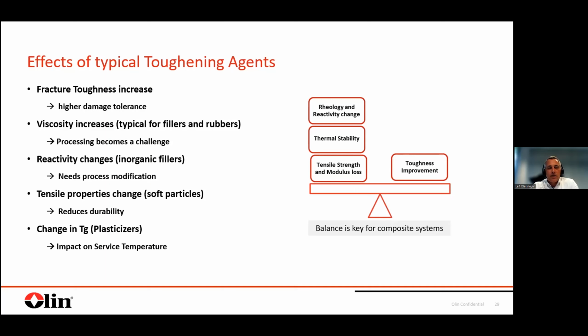Usually you are targeting to increase the fracture toughness of a system in order to achieve a higher damage tolerance. But typically what could happen is, for example, a viscosity increase, for example by fillers or rubbers. It could be changes in reactivities if you're using inorganic fillers that have particular surface chemistries. It can be tensile properties change in case soft particles or soft phases are used, and this can have impact on the overall composite properties. And last but not least, plasticizers, which can also be a method to achieve toughening, would have an impact on the glass transition temperature, and so finally on the service temperature of the tank. So in the end, we need to consider all these different parameters.